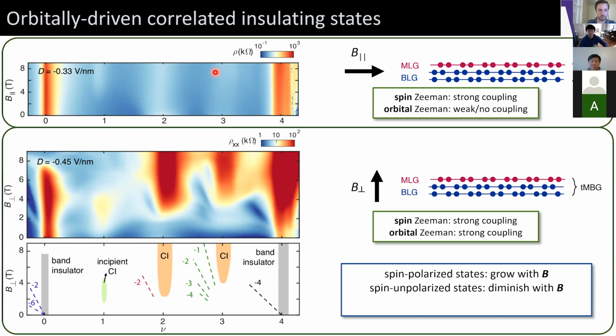We see a state that emerges above some critical field in a perpendicular field configuration, but not in a parallel field configuration. So what we think instead is that these are actually field-assisted, orbitally driven correlated insulating states. And these emerge only above some finite B perpendicular, which is coupling strongly to the orbital degree of freedom, whereas B parallel does not.